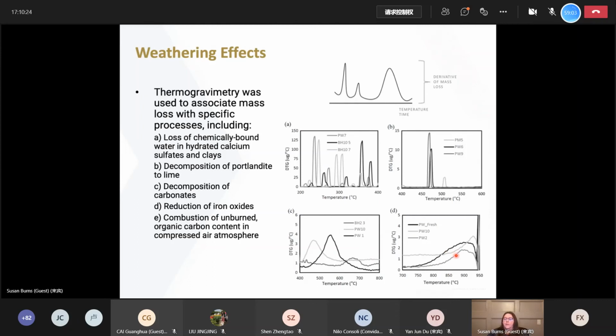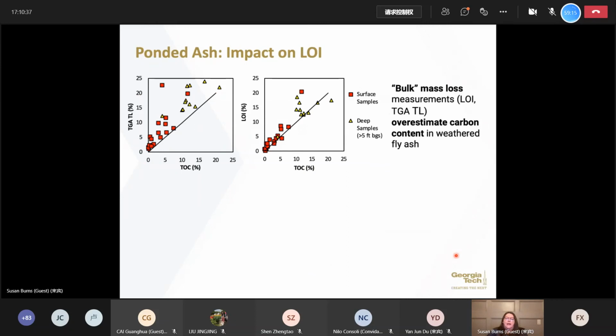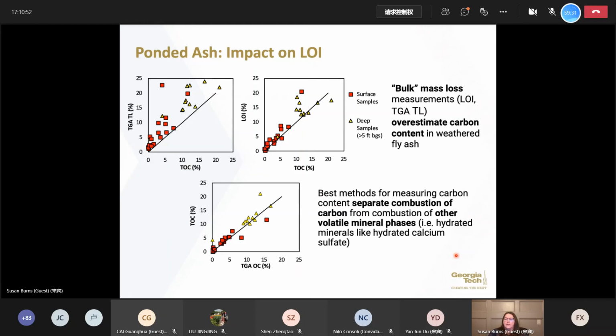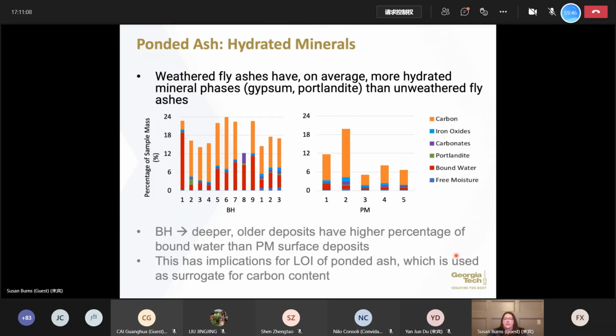And then we can come in and we can combust the remaining unburned organic carbon content by switching the atmosphere to compressed air. So the beauty of this is it tells us exactly where the mass loss is coming from in each of these samples. And so what you'll see is that when we look at this and we use what I'll call bulk mass loss measurements, things like loss on ignition, they're going to overestimate the carbon content in our weathered fly ashes. What we need to do, because these typically have so many hydrated mineral phases, is we need to come in and we need to study them either with a total carbon content measurement or with TGA. In all of these cases, we want to separate the combustion of carbon from other volatile mineral phases. And I'll show you here why that is.